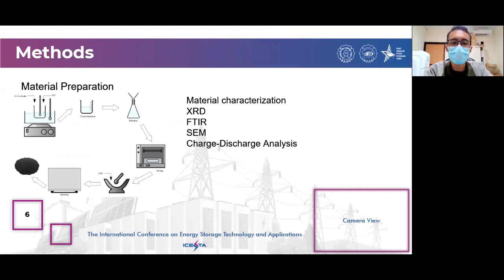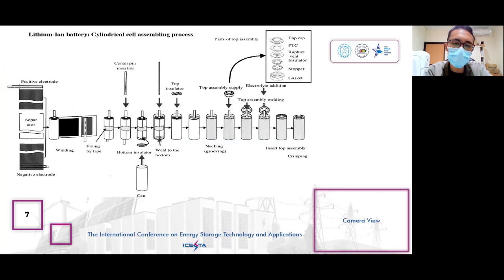The NCA precursor was synthesized by co-precipitation method using oxalate and then heated two times at high temperature, and the NCA material was analyzed using XRD, FTIR, and SEM. The NCA material was then assembled into a battery and tested for battery performance.